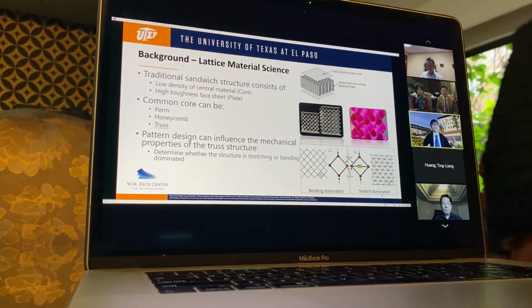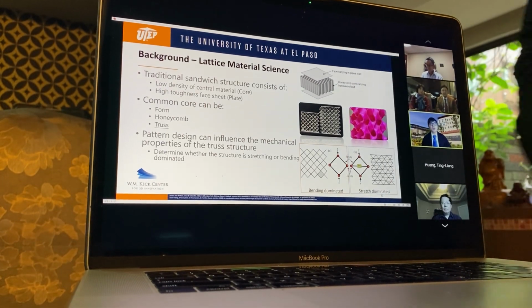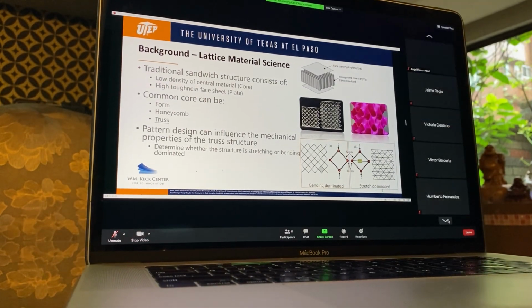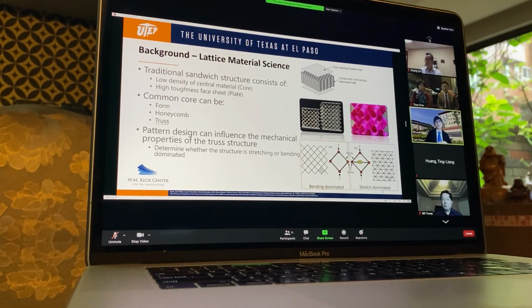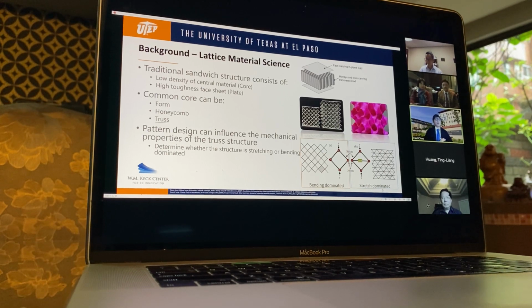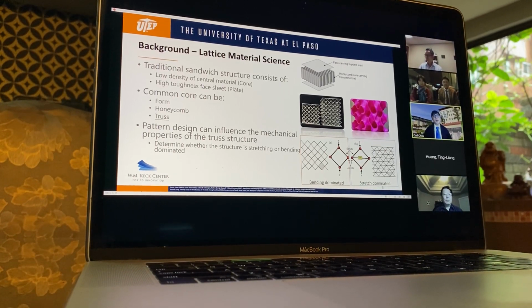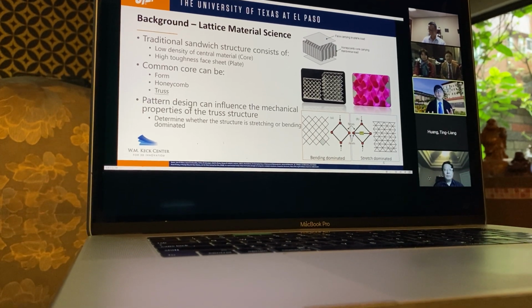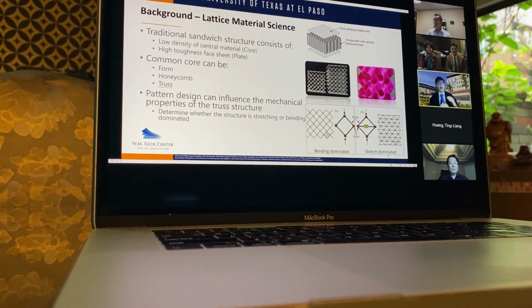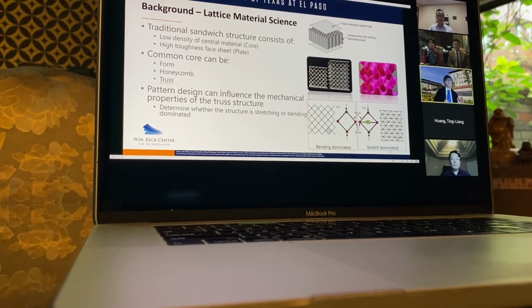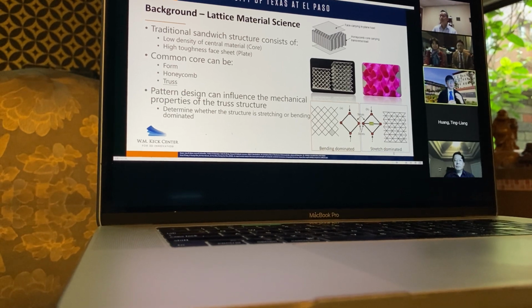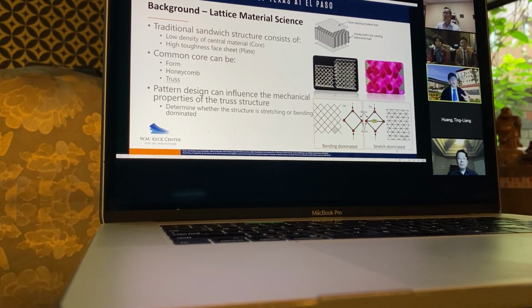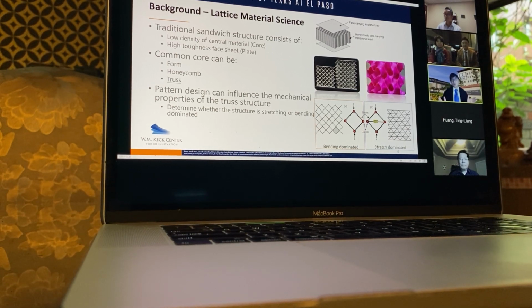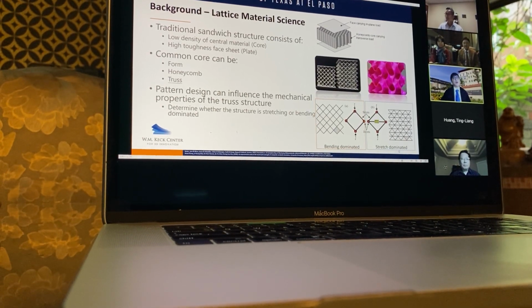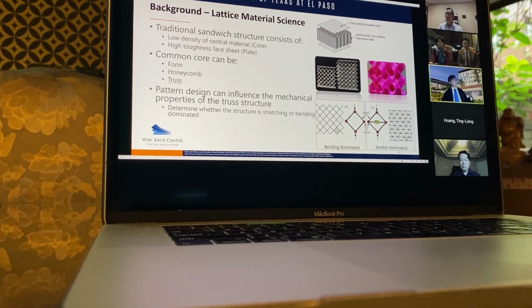So in this slide, I would like to talk about the enhanced design of lattice structure. This is the basic theory of our research. That's how we use lattice structure to enhance or improve the mechanical properties. In the past, the sandwich structure was able to provide high toughness and a high energy absorption ratio. A sandwich structure consists of a core, which is a low density material meant to absorb the external impact, and the plates on the top and bottom, which are used to uniformly spread out the stress or strain to the core. The core can be foam, or it can be a truss structure.